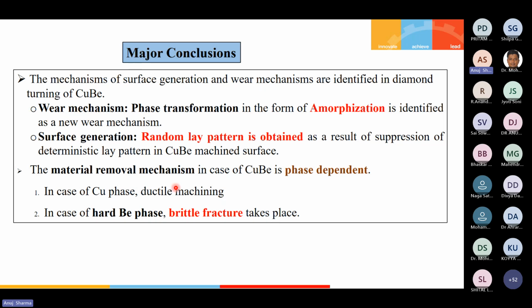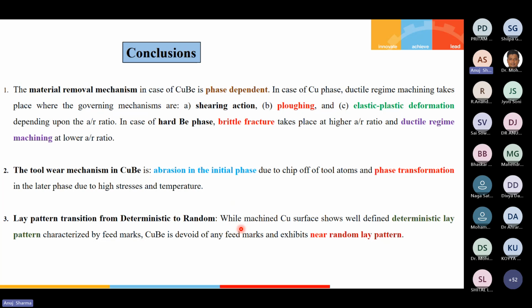The material removal mechanism in copper beryllium is phase dependent, which means that in the copper phase, the ductile machining mode was observed, whereas in the hard beryllium phase, brittle fracture took place. In copper, there was shearing action, plowing action, and then elastic-plastic deformation depending on the A/R ratio. In the hard beryllium phase, there was brittle fracture. And if we lower the A/R ratio, we can have ductile regime cutting conditions as well.